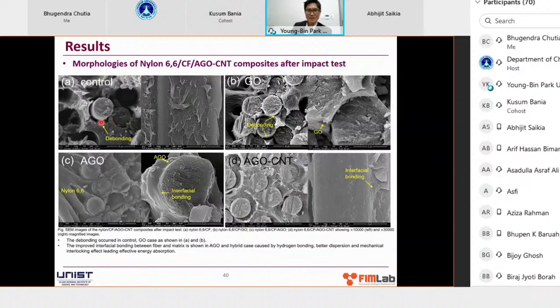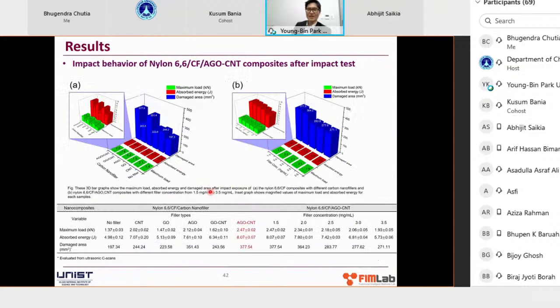In the control sample, we have a very poor interface between the fiber and the resin, evidenced by this debonding. But with the nanotube or graphene oxide inclusion, we have very good bonding between the fiber and the resin. Okay, so I'm sorry I had to rush through, but all of these led to significant improvements in the mechanical properties, both static and dynamic.